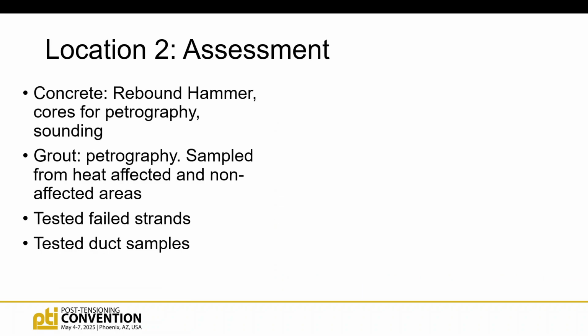So on the concrete assessment, we did a rebound hammer, which is not my favorite tool, just because it's impossible to correlate a rebound hammer number to a compressive strength, but it is a pretty good tool for a relative comparison of a large area. And there's a testing protocol, and you do, I think, 16 little impacts at each location, and you take out the high and the low and do that sort of thing. And we were looking for areas of surface weakness, right? So that we could focus our coring and concrete petrography efforts in those locations.